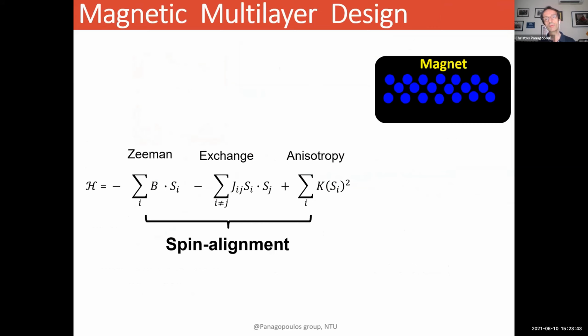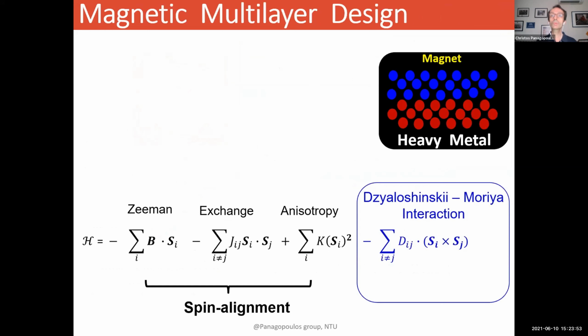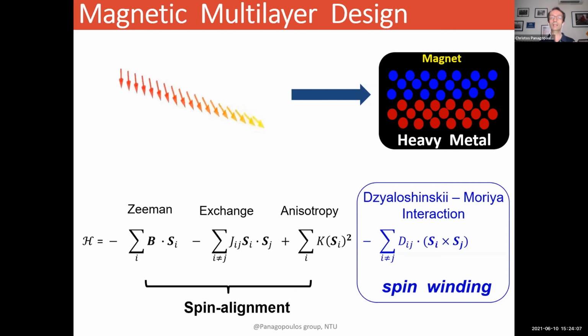Now we know that if you have a magnet, a standard system, the reason that you can have spin alignment is because there is a good balance between Zeeman, exchange, and anisotropy. If I add a heavy metal next to this magnet, then I induce a so-called Dzyaloshinskii-Moriya interaction, which is the cross product of the spins next to each other, i and j. And this would give rise to spin winding in my ferromagnet. So this is how a domain wall or a spin winding would look near the interface of this bilayer of a heavy metal to a magnet.